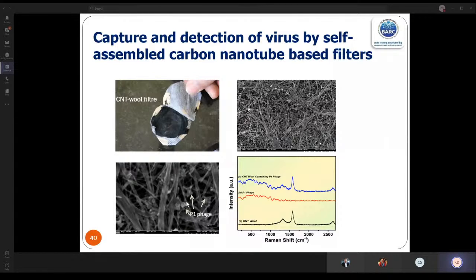There is one virus called P1 phage. So we have shown they have a similar size. So this P1 can be easily trapped in the carbon nanotube based filter. And after trapping, we can characterize them with Raman spectroscopy. Here I have shown that carbon nanotube will have its signature. This is the typical P1 phage signature. And when it is trapped, we can find out whether it is trapped or not.